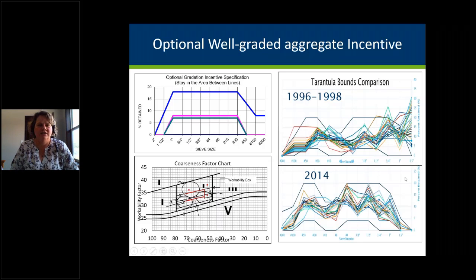Now, we don't require the contractors to give us a well-graded aggregate. We give them an option to do that. The reason we do that is the nature of the aggregates in our state. Not every part of the state has that intermediate type aggregate that can meet our well-graded aggregate incentive. And so we decided that we did not want to limit them and require it. We did go through a point in time where we did require it on a few jobs, and it actually pushed the contractor into struggling a little bit more. They were using 6 aggregates to get the surface closed up and get a decent ride.